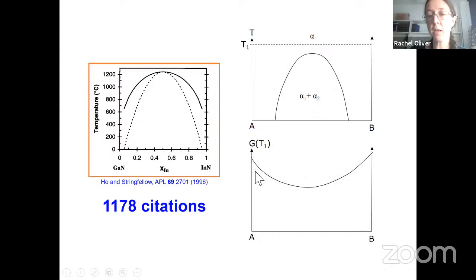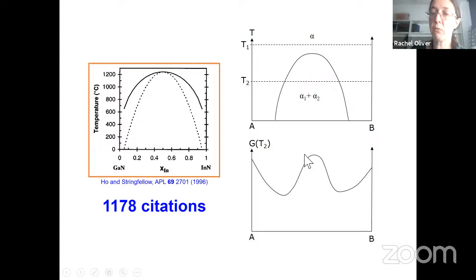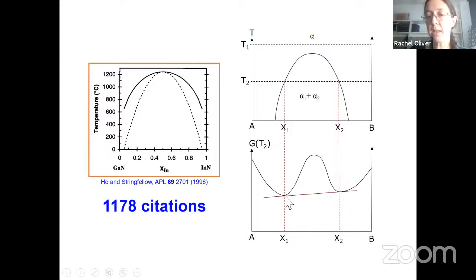That's because at the high temperature, the energy of the material, as it varies with composition, so this is now the Gibbs free energy of the material against composition, it varies with composition, but in a way that there's just one minimum. Whereas at a lower temperature, the Gibbs free energy versus composition curve varies differently. So we can see it has two minima and a maxima. So what this is saying is that for the phase alpha, having all the material just mixed up and being all randomly mixed together would have quite a high energy. But if we split up into these two separate phases, one with a lower composition than the average composition of the alloy, and one with a higher composition than the average composition of the alloy, we can lower the overall energy. We can split up into two low energy phases rather than having one high energy phase.